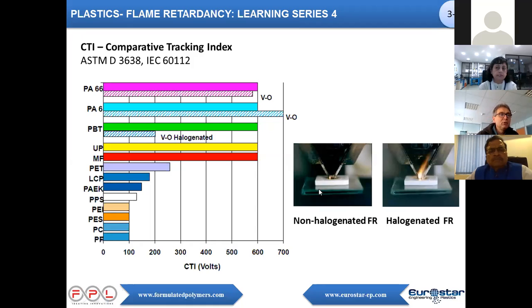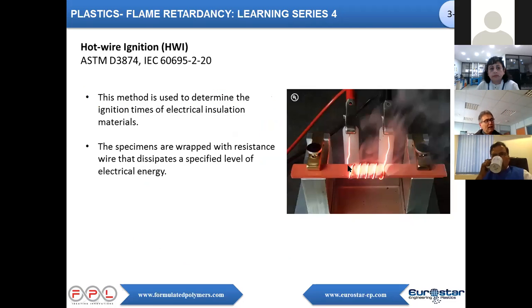On the small picture, you will see the behavior of a non-halogenated flame retardant. Typically, you see a few generations of flames. It's very small, and very often non-halogenated materials have very nice CTI, sometimes 600 and above. For halogenated FR, you most of the time have creation of a conductive part, and the CTI is more limited, around 300, 400 volts.